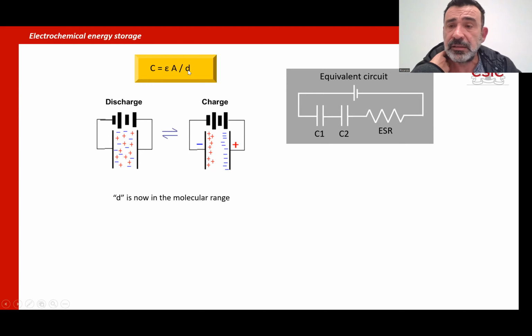The distance in a capacitor was the distance between the two aluminum plates, which is in the millimeter scale, more or less. But now the distance is between the electrode, one of the aluminum plates, and the charges, the positive or negative charges stored on the surface of the electrode. Now this distance D is in the molecular range. We are moving to nanometers, not millimeters, and we are increasing the capacity by several orders of magnitude.